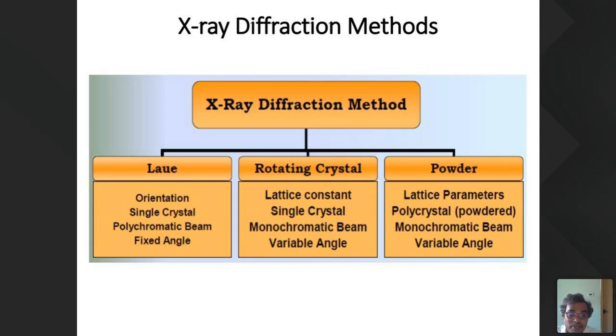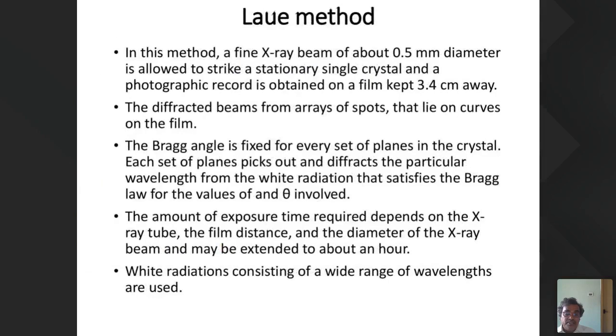Okay, X-ray diffraction, there are 3 methods: Laue method, rotating crystal method, and powder method. So we will study one by one in detail. In the Laue method, an X-ray beam of about 0.5 mm diameter is allowed to strike a stationary single crystal. The photographic record is obtained by a film about 3.4 centimeters away. The diffracted beams form arrays of spots that lie in curves on the film.